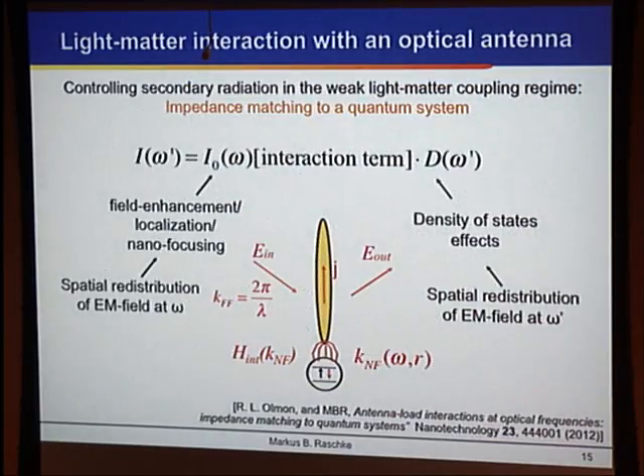There is a quantum optic analog to what I just described, and this is actually an extension to this, which was developed by one of my students, who is an electrical engineer, who really had the idea: what are we actually trying to do if we're trying to locally excite an optical transition here, say, think about a two-level atom, and we try to do this in this localized form? Then clearly there is also a question of how often can I cycle this atom through an excitation emission process. And this is also what ultimately limits your sensitivity. And it actually turns out, we found this experimentally, that the sharper we make the tip, the higher sensitivity we get. And at first, people thought this has to do with your local field enhancement being larger.